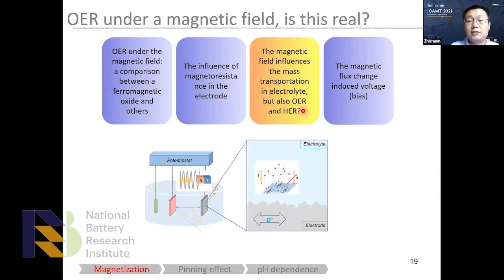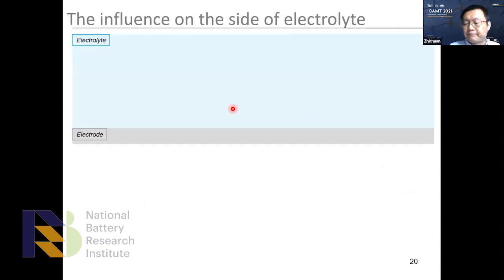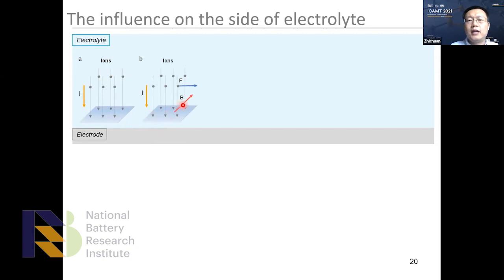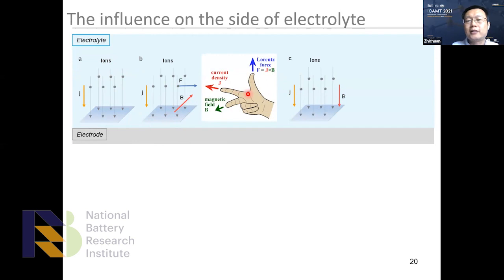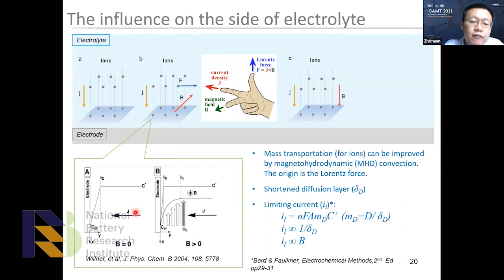And then we have to look at mass transportation to exclude that possibility as well. We know that if this is an electrode surface and this is an electrolyte, during the reaction, charged species, for example ions, will move towards the electrode surface. So in this case, if I apply a magnetic field, the Lorentz force will be applied. The Lorentz force does not do work, but it will change the direction of the movement of ions, right? And if the magnetic field is in the same direction as the ion movement, there is no Lorentz force. So this is something known: the magnetic field and Lorentz force will improve the mass transportation of ions near the electrode surface. For example, they can shorten the diffusion layer. In this case, the limiting current can be improved, or let's say the kinetics we observe on the electrode can be improved.